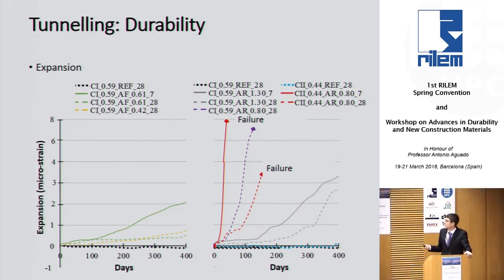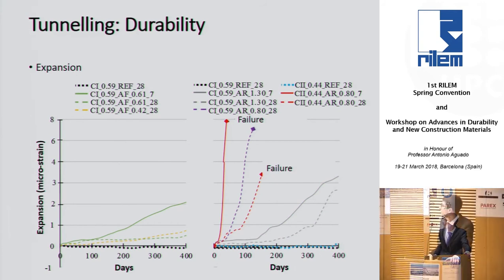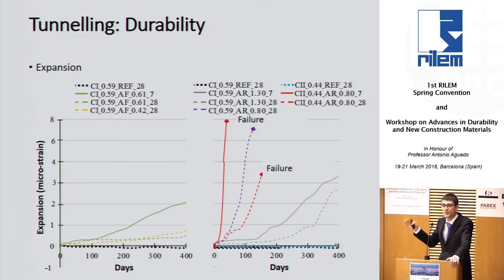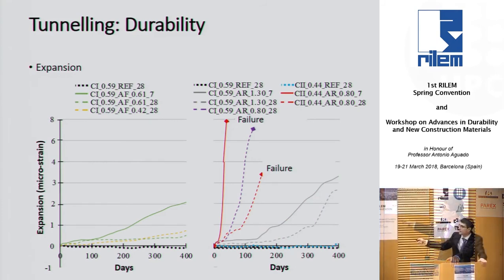When we continue the accelerated testing and measure the expansion, we saw that the difference between an alkali-free and an alkali-rich was there. So you see here the expansion curves depending on the days of exposition. Right? These curves here, on your left, are for the alkali-free accelerator. And on the right, you have the alkali-rich accelerator. I have to say that all the cements used here may be classified as sulfate-resistant. So you see that many of the specimens, in the case of the alkali-rich, fail, but you have big expansions for the alkali-free condition also.